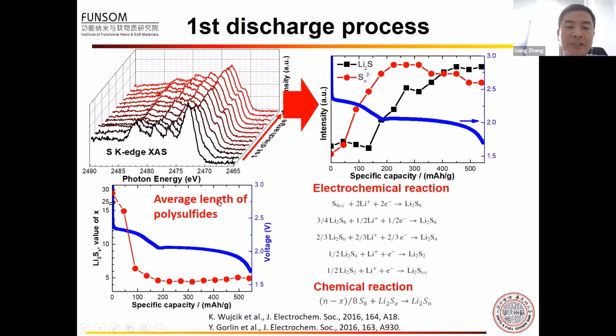We also calculate the average length of the polysulfide using the method I mentioned above. We can see here at the beginning, the average length of polysulfide drops very fast and then comes to an almost constant value. This also indicates that at the beginning, the electrochemical reaction is dominant with the formation of lithium polysulfide. In the intermediate discharge process, the electrochemical reaction and the chemical reaction can both happen, and these two reactions come to a balance, and therefore the average length of polysulfide doesn't change very much. And at the end of the discharge process, the average length of the polysulfide is around 5. This indicates that the polysulfide at the end of the first discharge is not fully converted to lithium sulfide.